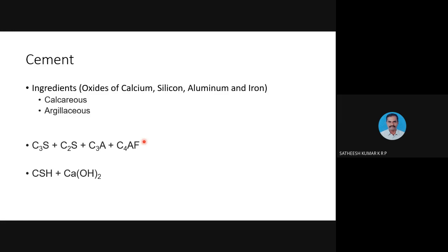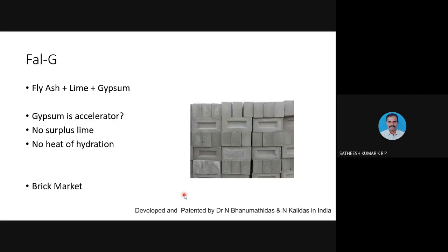Sir, like the fly ash bricks mentioned here, we are using only fly ash with lime, where no cement is involved. If cement is involved, then the chemical reaction itself is different. In fly ash we have silicates, and in lime we have calcium. These two will react to form the calcium silicate components. Whereas in cement we have the Bogue compounds, and a separate reaction will keep on going. And the excess lime from the hydration of the cement will also be consumed in this reaction.